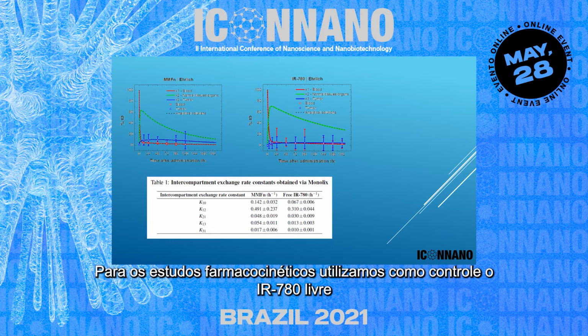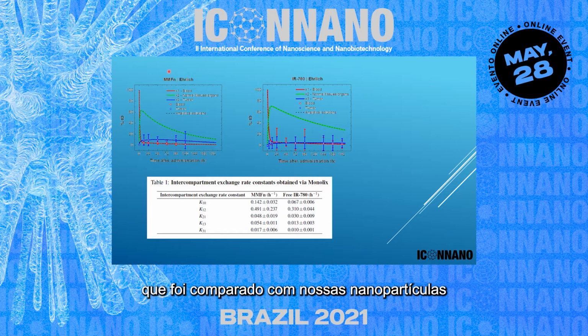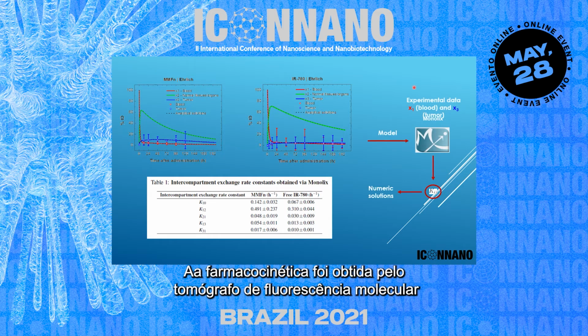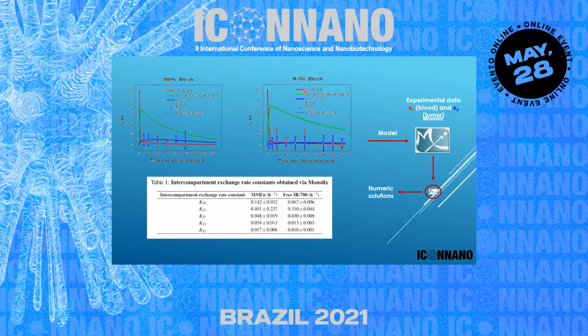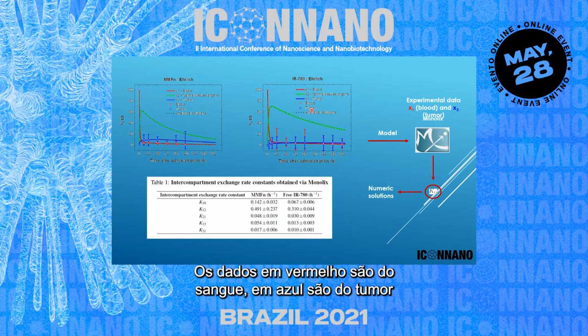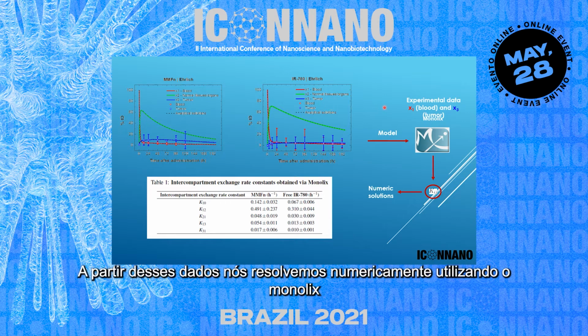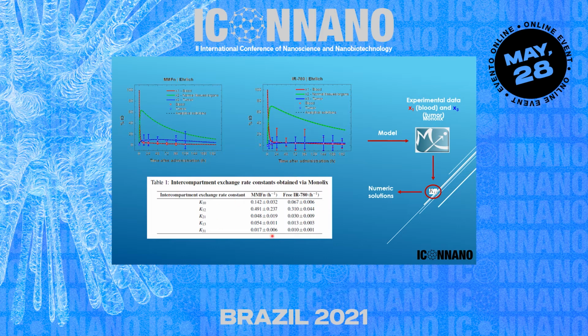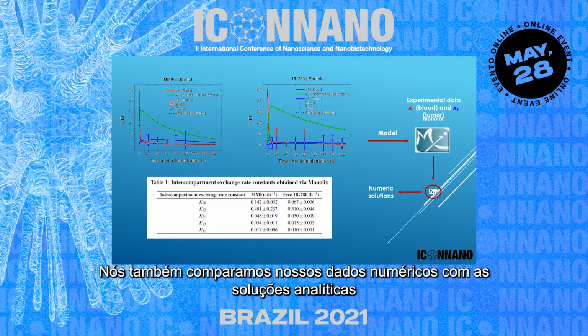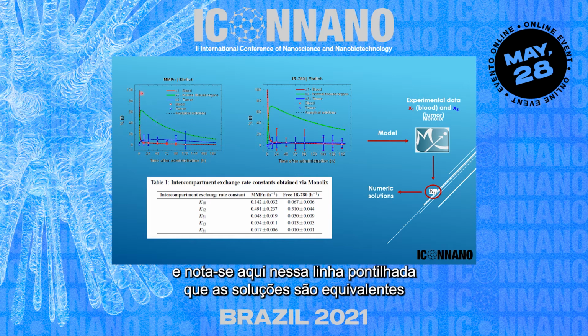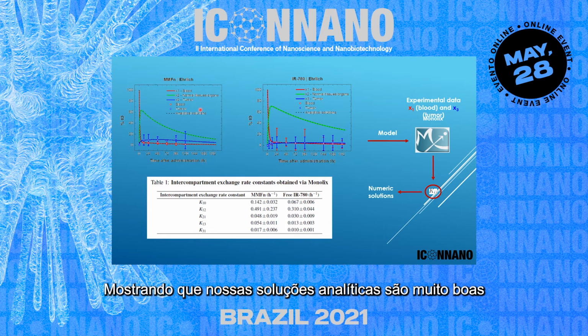So for the pharmacokinetic studies, we use a control, free IR 780, which is compared with our nanoparticles. We obtained the pharmacokinetics by fluorescence molecular tomography; the data in red is for the blood, the blue is the tumor, okay? From this data, we solve numerically using MonoLix and obtain those parameters here. We also compare these numerical simulations with our analytical solutions, and you do see here in dash that the solutions are equivalent, showing that the analytical solutions that we obtain are very good.